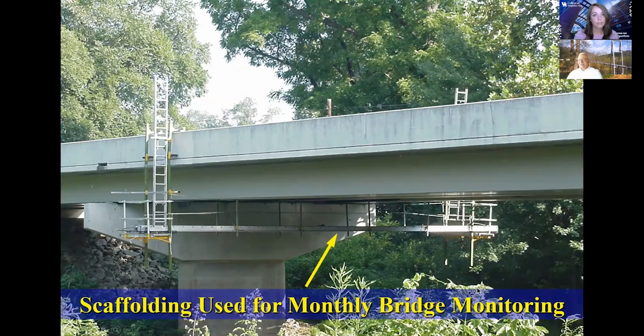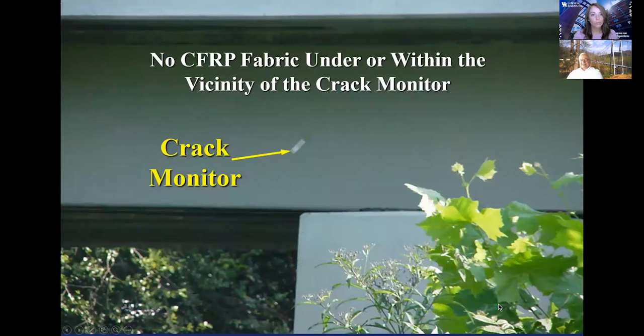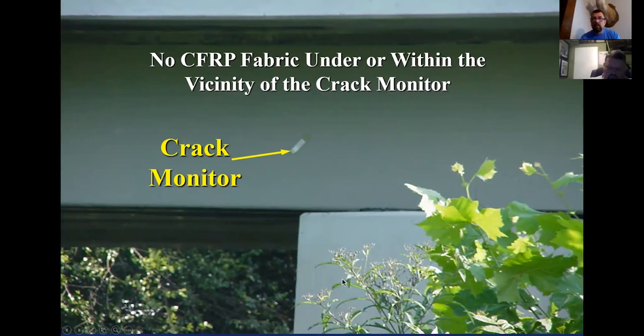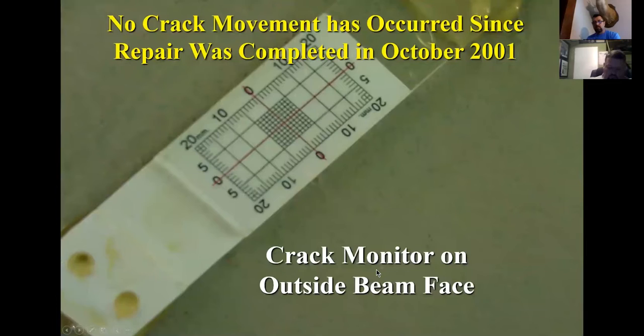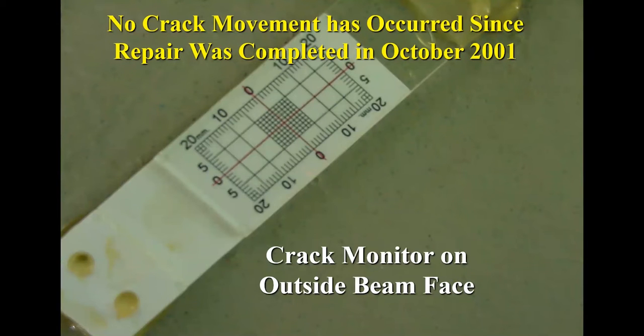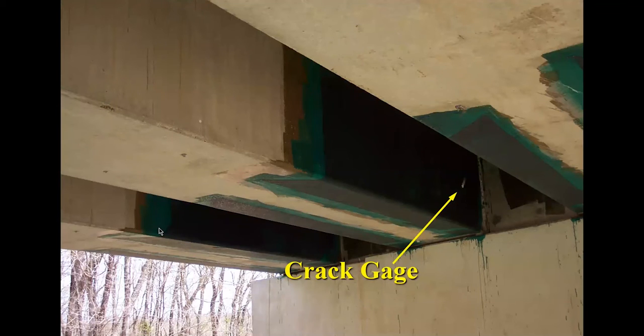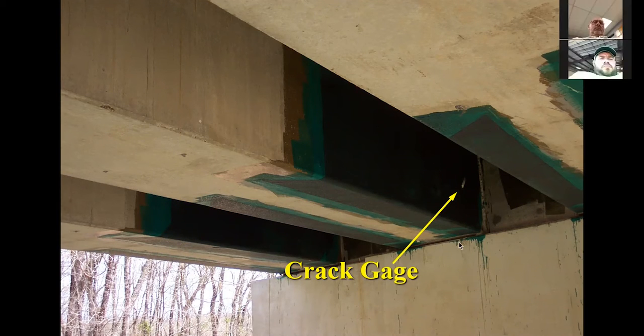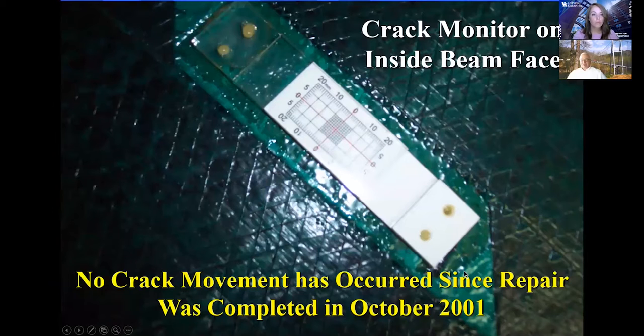And we monitored the bridge for 3 years. Now remember, this is in 2002. People could not believe that something as thin as this material can really save this bridge from those cracks. We put crack gauges at each and every crack and on both sides of the beam. And on the inside, the repair looks as such. And the crack gauges, we have not seen any movement in these crack gauges since 2001. Which means that the repair has done its job.